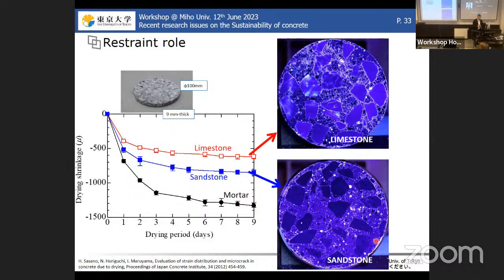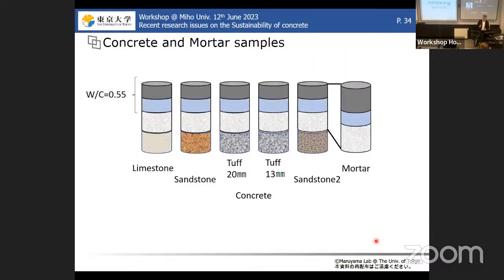It has an influence on some concrete properties. So then I made five different concretes whose volumetric mixture proportion is completely the same, but only the coarse aggregate was changed. And I also made a mortar whose volume mixture proportion is completely the same as that of the mortar part in the concrete.